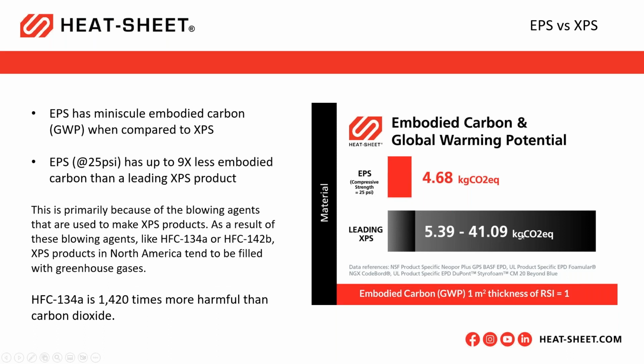This is the measurement of GWP, embodied GWP. As you can see, depending on how the XPS is made, it's from either 5.39 to 41.09. The EPS that we use in HeatSheet is lower than the lowest and up to 9 or 10 times lower than the highest. And it's all got to do, I think, mostly with the blowing agents that are used in the XPS product. So in addition to everything else, it has lower global warming potential and less embodied carbon.